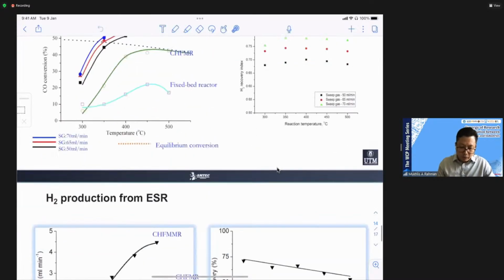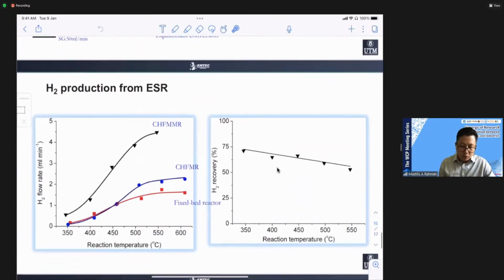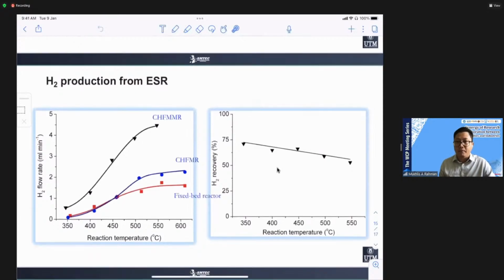So test again with ethanol steam reforming. This time we didn't draw the equilibrium line because ethanol steam reforming is an endothermic reaction. So the equilibrium conversion for ESR is equal to 1 at whatever temperature. So the higher the temperature, the higher the amount of hydrogen produced. But again, when we use the palladium membrane on the outer surface, we managed to get more hydrogen compared to the one that doesn't have a membrane in the fixed bed reactor.